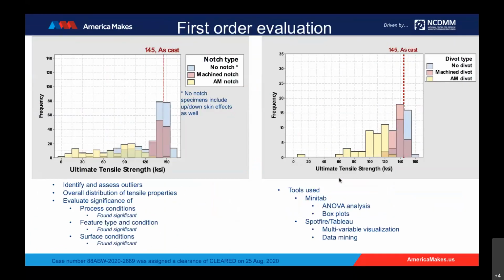Next slide, please. So just to quickly go over a first order evaluation of this data, if you were to pull all of the data and then segment it by the different notch types and different divot types. For the notch data set, we ended up having specimens with AM notches, and to decouple the effect of the notch geometry and the AM surface finish, we came up with baseline specimens which had the same notch geometry machined into them. That way we could uncouple the effect of the AM finish, and then to further baseline it, have a specimen with no notch,